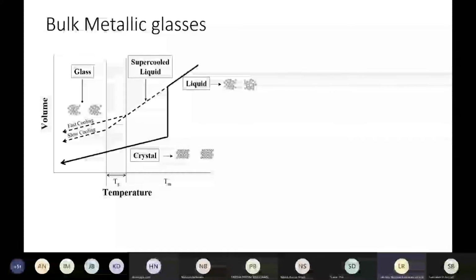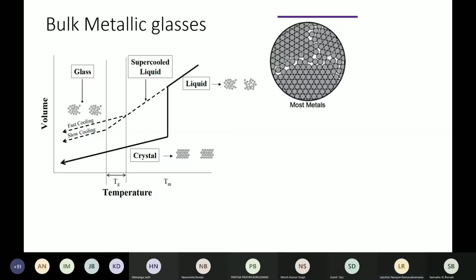This is again very well known in polymers, and I'm not aware how many people have learned about polymers. But essentially what happens is you avoid crystallization, although that is the most likely process available to the material. It is thermodynamically favorable for a material to become crystalline rather than a glass. But if you can rapidly cool it, you can still preserve the structure of the liquid.